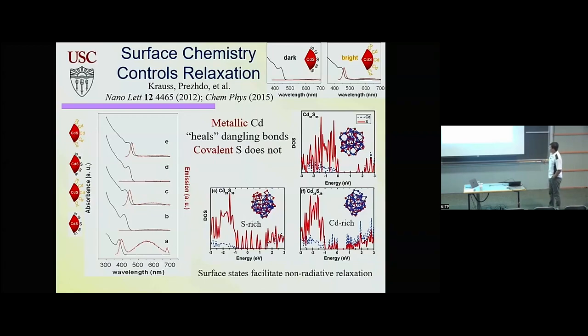And then he can add cadmium on the surface, and he recovers luminescence. And if he puts sulfur on the surface, it's gone. So chemistry is very important. And the explanation is quite simple, because when you have metal on the surface, which is good, metal rich, metals heal dangling bonds in a very efficient way because they have d electrons. They can make metallic bonding. It doesn't have to be directional. But sulfur has more limitations on how it can heal unsaturated chemical bonds, and sulfur on the surface creates many, many trap states across the band gap. The metal on the surface creates trap states too, but they heal. They create a little subband, and a substantial energy gap is still maintained. And it's emission from the subband that is responsible for this feature that is seen in experiments.